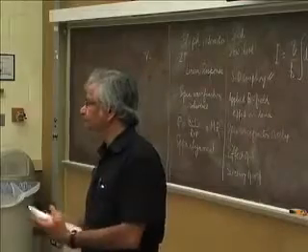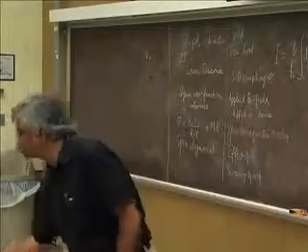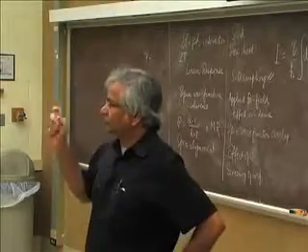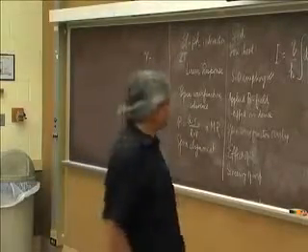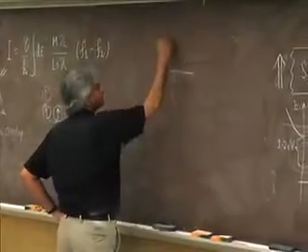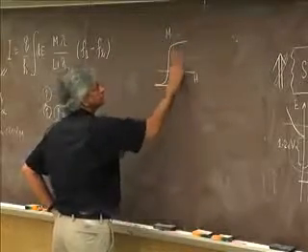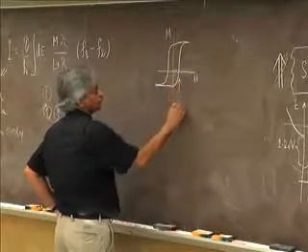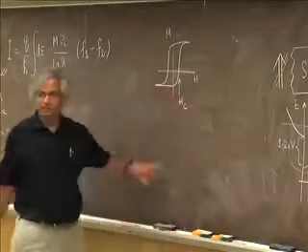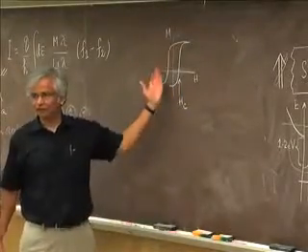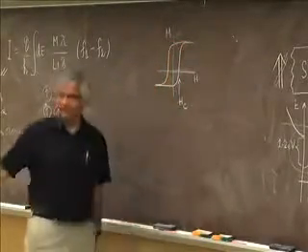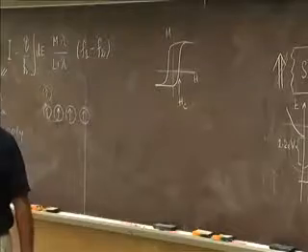Yeah. There will be a problem, like the thermal fluctuation being enough to switch a nanomagnet, or no, usually the two parameters people talk about with magnets is this M versus H, which they draw. So they talk about the coercive field, which is the field you need to switch it from one side to another, and then the total magnetization, the saturation magnetization. Those are the two numbers usually given.